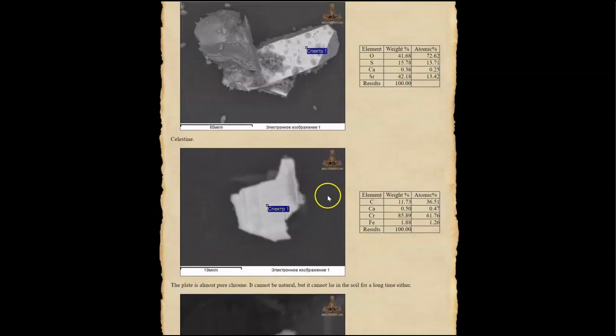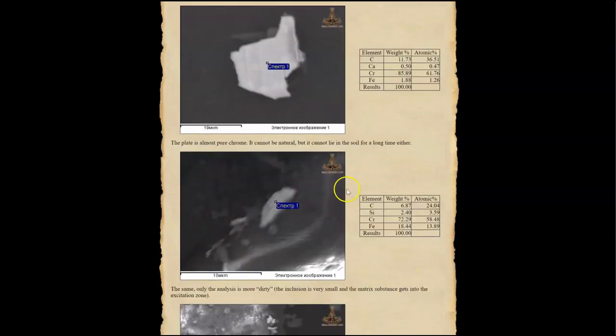And this very unusual flake is almost pure chromium, 85.89% chromium, a very, very rare and unusual find indeed. This is another small flake of chromium, with more of the background matrix included.